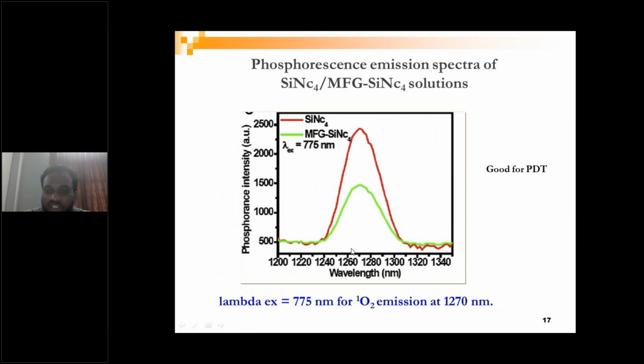Well, as it has silicon naphthalocyanine, we would like to check whether it could generate singlet oxygen or not. Because if it could generate singlet oxygen, then we can get a synergistic photodynamic therapy too. If you look at the spectra, this is the phosphorescence spectra of silicon naphthalocyanine, the red color, and MFG-SN means silicon naphthalocyanine functionalized multifunctional graphene. You can see that compared to SiNC4, it has less intensity, but it could generate singlet oxygen too. It is an indication that the peak there is a phosphorescence peak, which corresponds to singlet oxygen emission.